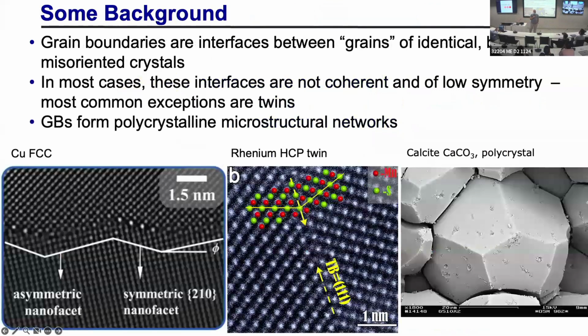Okay, so just a reminder. I spend a lot of time thinking about grain boundaries and other kinds of interfaces. So just as a reminder, a few pictures of some interfaces. When we talk about grain boundaries, we're just talking about the two-dimensional interface that separates the same crystal structure with different orientations. So it's the plane across which the orientation changes. And for this simple case here in copper, you can see that this grain boundary has a nominal grain boundary plane like that, but you see it's a little bit more complicated. You see facets, right? The actual boundary plane seems to go like that. It's actually very common, and this is on the nanometer scale.